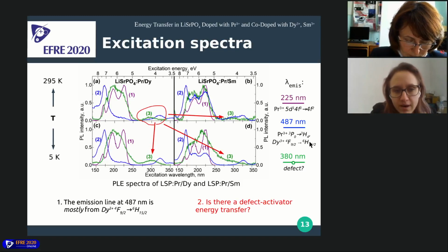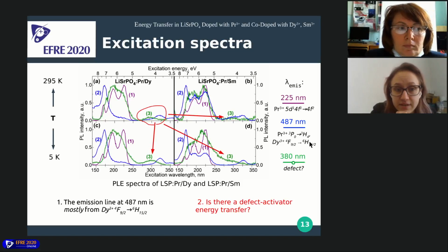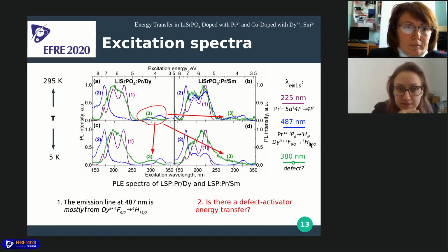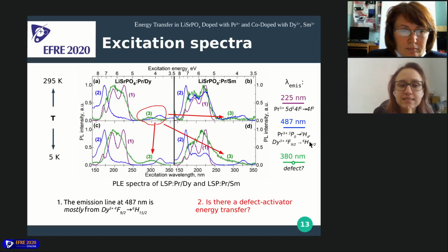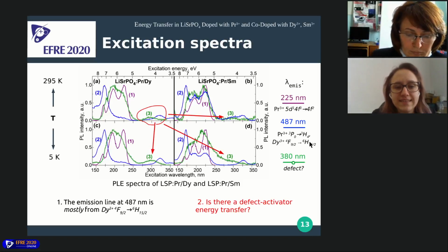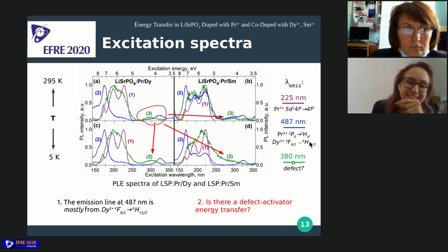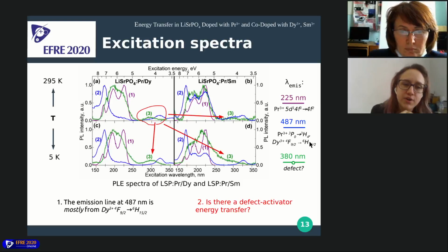Firstly, the blue lines on this spectra stand for praseodymium-3+ f-f emission at 487 nanometers. Dysprosium also has emission at exactly the same wavelength. So we want to distinguish praseodymium-3+ emission from dysprosium, and we can see that emission at this line is very weakly excited in the region of direct praseodymium-3+ excitation.